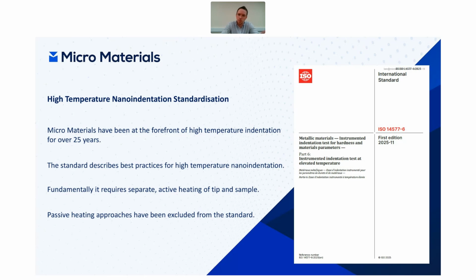So the standard is a follow-on from the first 5 parts of the ISO 14577 standard, and it describes the best practices for high temperature nano-indentation. A fundamental stipulation or requirement is that of separate and independent heating of the tip and the sample. Any approaches that involve passive heating of the tip have been excluded from the standard.